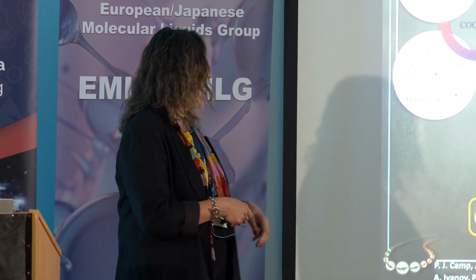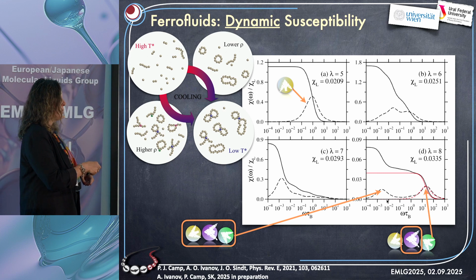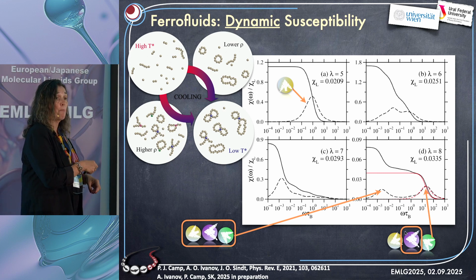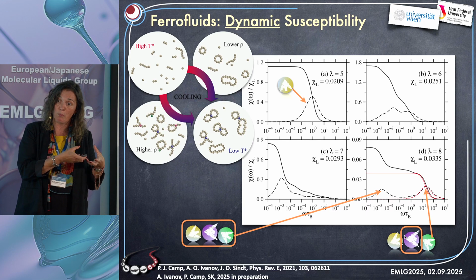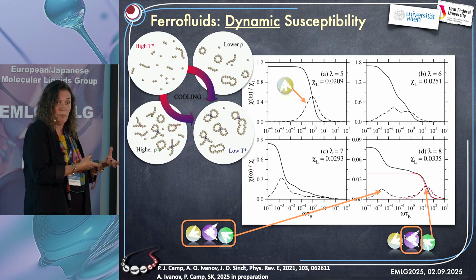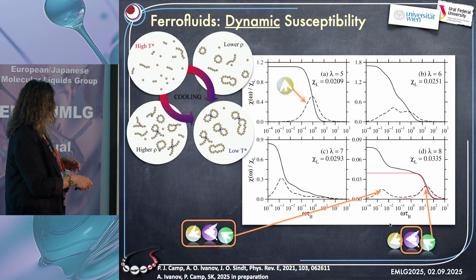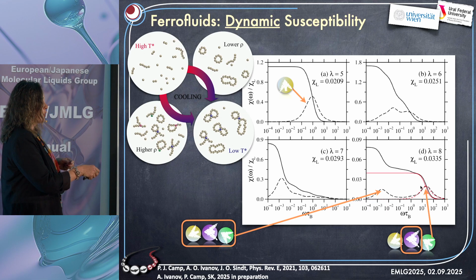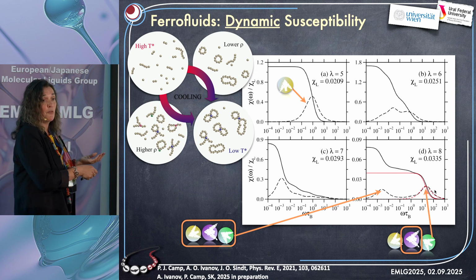If the particles are very strongly interacting and forming rings, in principle the frequency they are susceptible to is quite low. But the problem is that they are already clustered in rings, as we talked about previously, and this makes them magnetically very reluctant to the applied field. So you need a strong field. Instead, with those local frequencies, the whole cluster will not feel that kind of perturbation, but this oscillation will change. But then, again, you need a very high frequency.